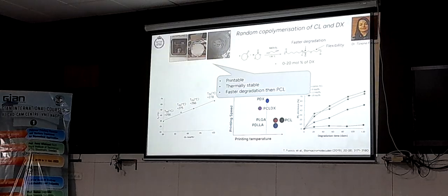I wouldn't say that the PCL reacts with the calcium phosphate. DCM might be evaporated and the percentage of solvent will reduce. Yeah. So then I think that may be the reason. Yeah, that would be my first guess. Because I have also tried PCL with chloroform, and I also got the same problem. After some time it gets a solid plastic structure.